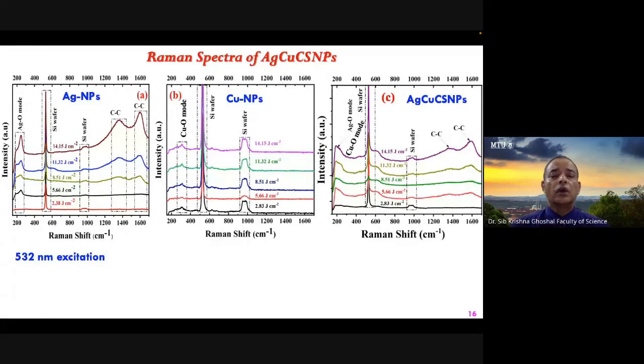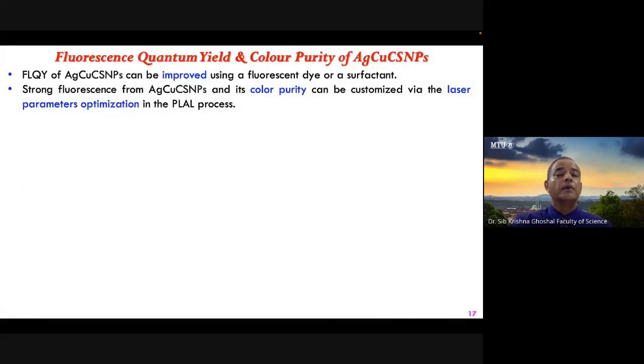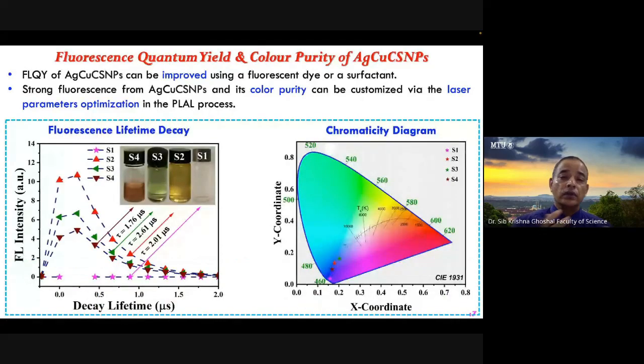When we go to the copper nanoparticles, we also see copper oxide modes. And these two modes combined together in the silver-copper core-shell nanoparticles will be very useful for the creation of reactive oxygen species. And again I tell you, the creation of a larger number of reactive oxygen species is the main game of this research, by controlling the fluorescence quantum yield and by controlling the color purity.